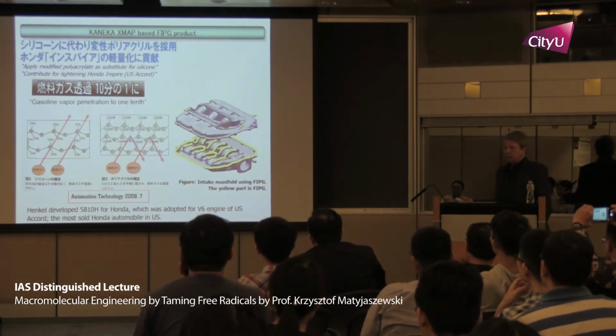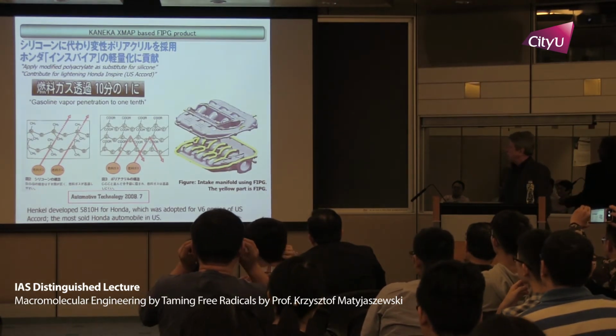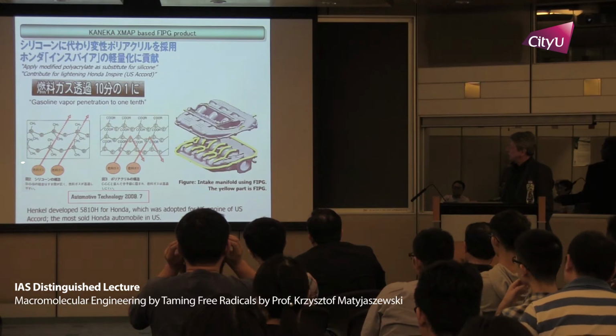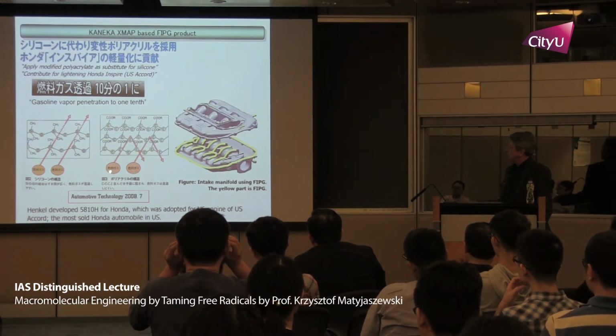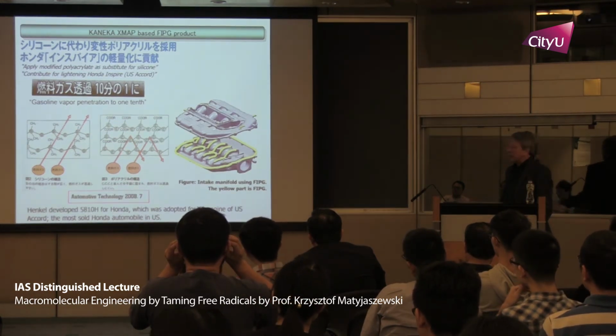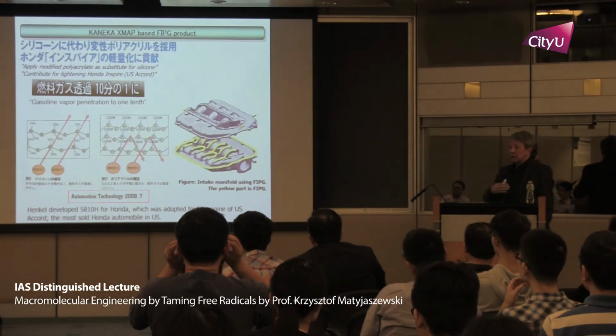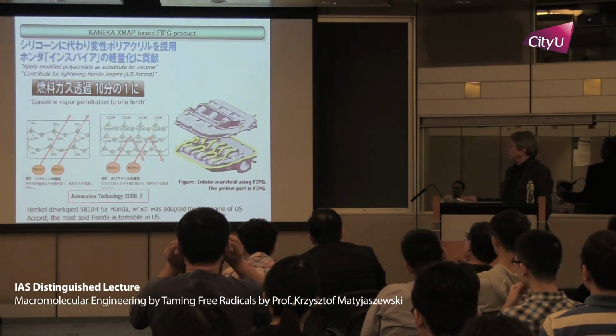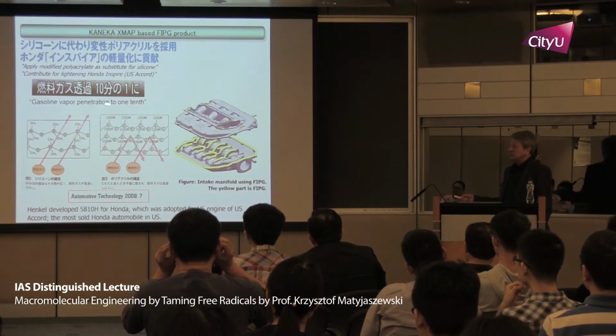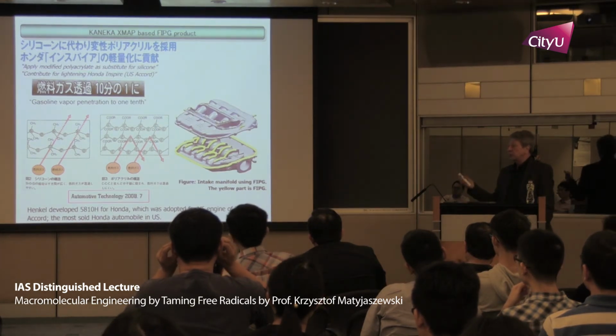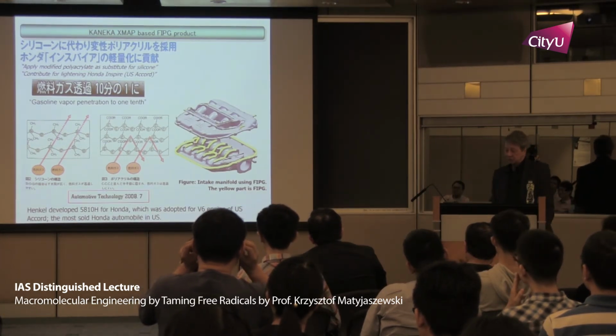So if you look at the gaskets in the intake manifolds, this is what happens with PDMS. This is what happens with the acrylate-based system. Much more polar, gasoline vapor does not pass through. So 10 times less loss of gasoline vapors. Good for environment and also good for the energy performance.